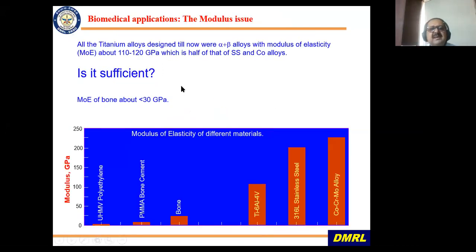The other thing about beta alloys is that they have a much lower elastic modulus, much lower than alpha phase also. And it is also much lower than stainless steel and cobalt alloys, which are also used as biomedical implants. Now, the modulus of bone is around 30 GPa. So the beta alloys have generally got modulus around 50 to 70 GPa, but more often 60 to 70 GPa. And it is better to have a modulus which is nearer to bone, then you don't have problems like load shedding and all.